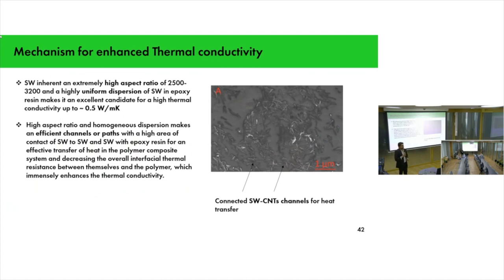So what's the mechanism for this thermal conductivity? Here we see that single wall has obviously a high aspect ratio, which is very important for thermal conductivity enhancement. And moreover, it is highly uniformly dispersed in the epoxy system. Here you can see there are efficient connecting pathways from carbon nanotubes to carbon nanotubes, and then the carbon nanotube bridging effect with epoxy resin for the effective transfer of heat in the polymer system. And then it decreased the overall interfacial thermal resistance, also called Kapitza resistance, between themselves and the polymer system, which immensely enhances the thermal conductivity.